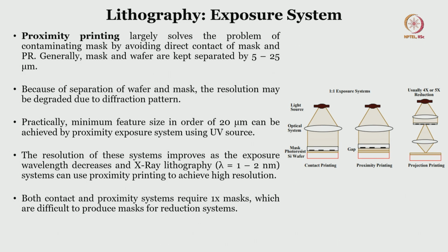In the case of proximity printing, we are now here, it largely solves the problem of contaminating the mask because it is not really in direct contact, and it is generally separated by 5 to 25 micrometers. That is why we call it proximity. Because of the separation of wafer and mask, the resolution may be degraded due to the diffraction pattern. Practical minimum feature size is on the order of 20 microns.